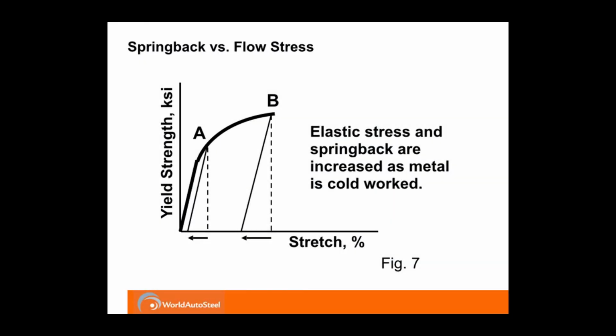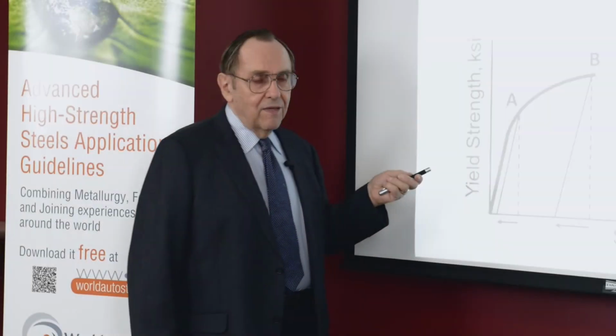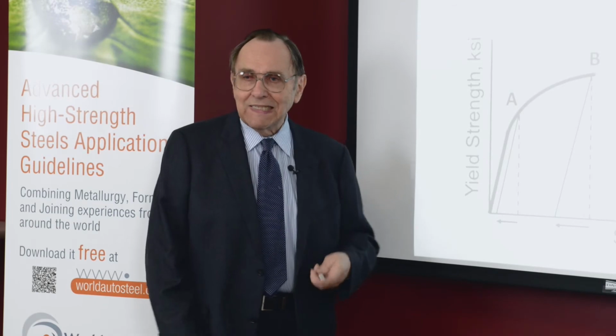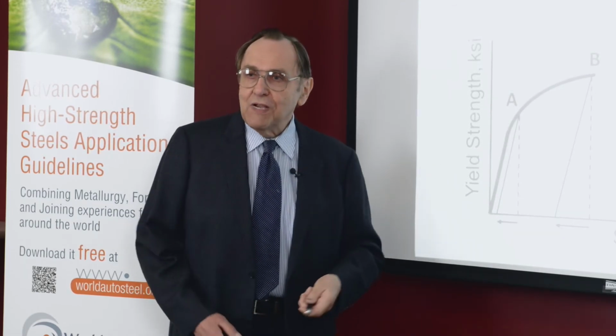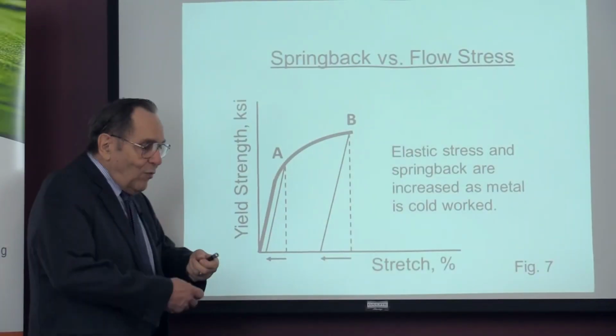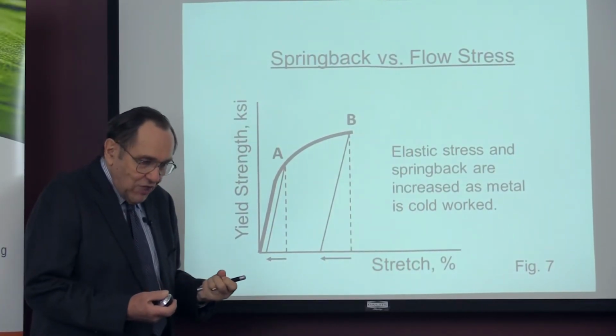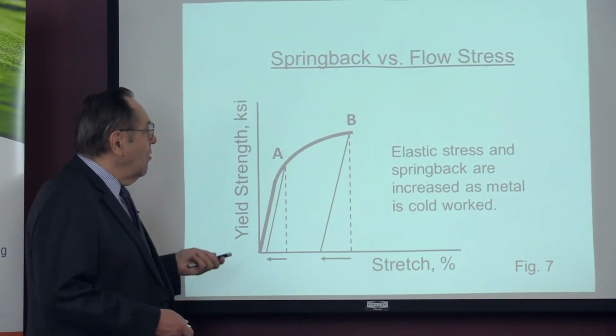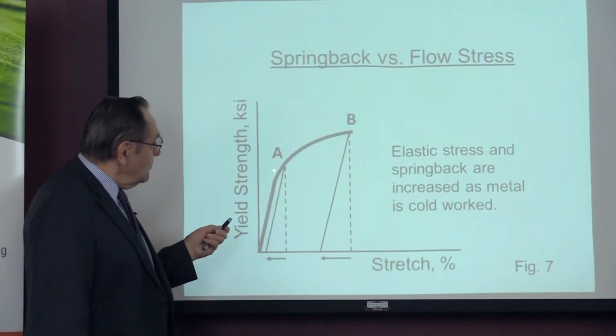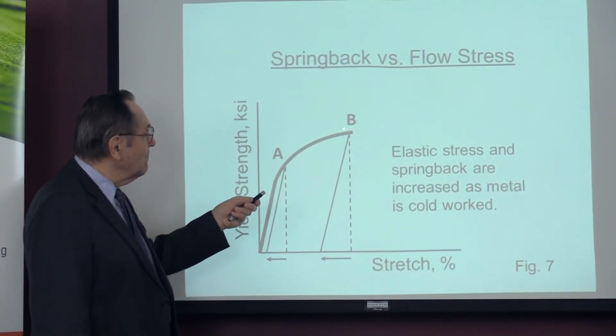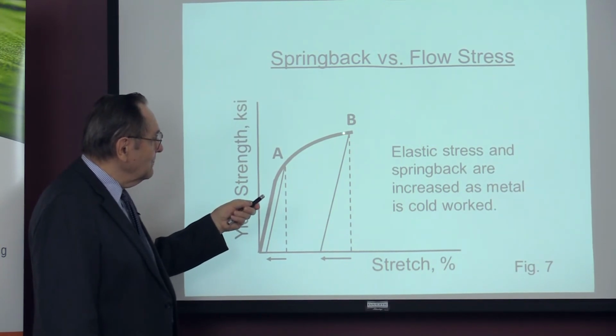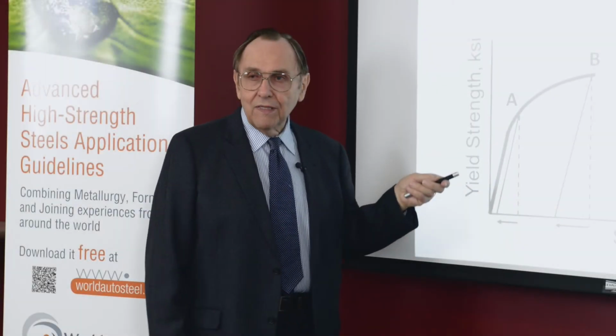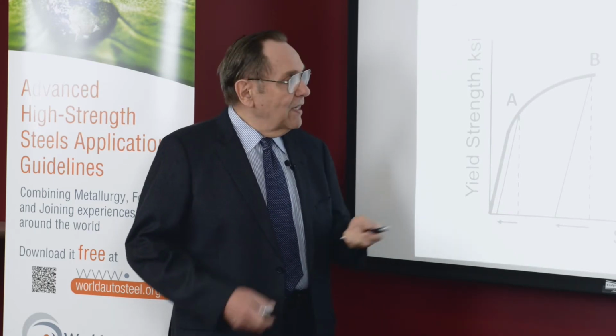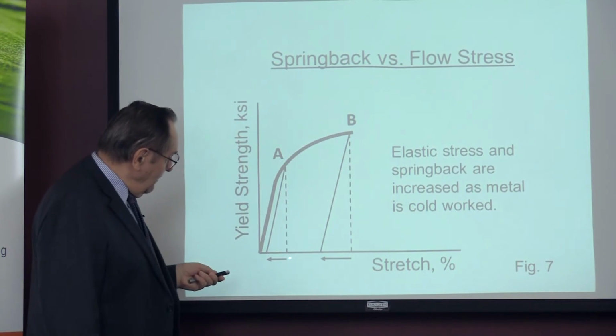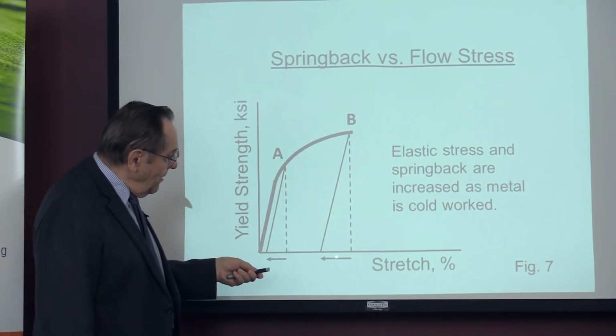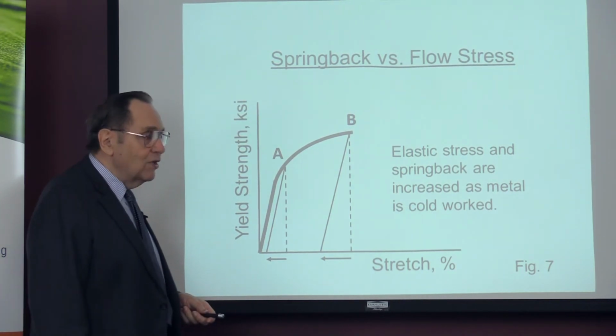Now, that is determined at this point here at the yield strength. But we do not make very many stampings that have no deformation in them, just the sheet of metal. And so when you start to deform them, to stretch them, to pull them over punches, or punches pushing them down, you now have an increase in the strength of the material. The yield strength increases, but the elastic portion goes along with it because you're adding more force, you're adding more elastic stresses. And now, instead of this amount of springback in the stamping, you have this much. So you have increased your springback.